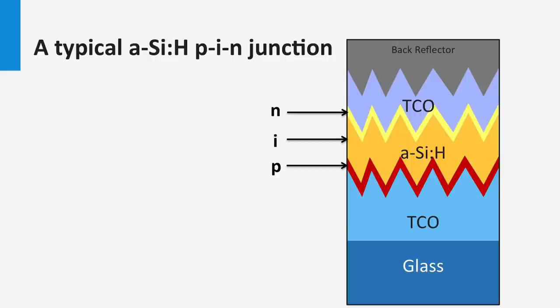P-doped layers are boron-doped amorphous silicon, but higher bandgap materials such as boron-doped silicon carbide and silicon oxide layers are also used to enhance the transmission of blue light into the absorber layer. As a back reflector, a TCO metal back reflector is typically integrated into the device. Metals used are either aluminum or the more expensive silver, which has higher back-reflection compared to aluminum.